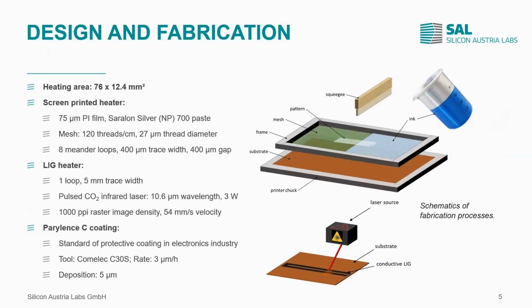Good, so let's take a look at what we have done actually. We fabricated one printed heater. Of course, we fabricated more samples, but one sample was printed with the outer dimensions of 76 by 12.4 millimeters square, and an LIG heater with the same outer dimensions in order to achieve similar resistance values. The screen printed heater and the LIG heater were both fabricated on 75 micrometer thick PI substrate. The printed one with a silver nanoparticle ink and the LIG one with a CO2 laser and 1000 ppi image raster density at the power of 3 watts.